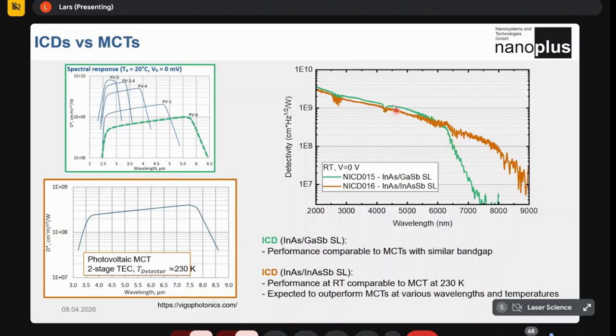Just quickly, there's 2 technologies, gallium antimonide and indium arsenide antimonide. And you can see here the cutoff for the first is somewhere at 6 micrometers, and the cutoff for the second is here somewhere at 8 micrometers. So that would be a nice replacement for the MCT detectors. They work at room temperature, and this kind of technology can be used. We use it ourselves for our own purpose. We don't have it as a product at the moment because we're concentrating on lasers, but also this is possible with that kind of technology.